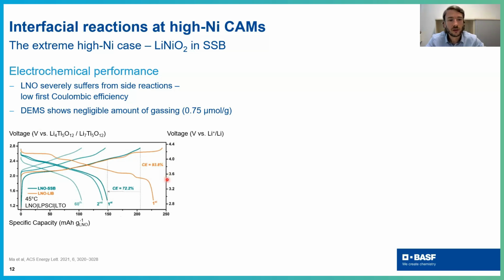Now, if you compare this yellow profile to this green voltage profile, you see that first of all, the coulombic efficiency is much lower. It is just 72.2% in the first cycle, meaning that there's a lot of loss of active lithium which you reintercalate, but also the charge capacity is quite low. And for sure the discharge capacity is very low. It's 150 milliamperes per gram.